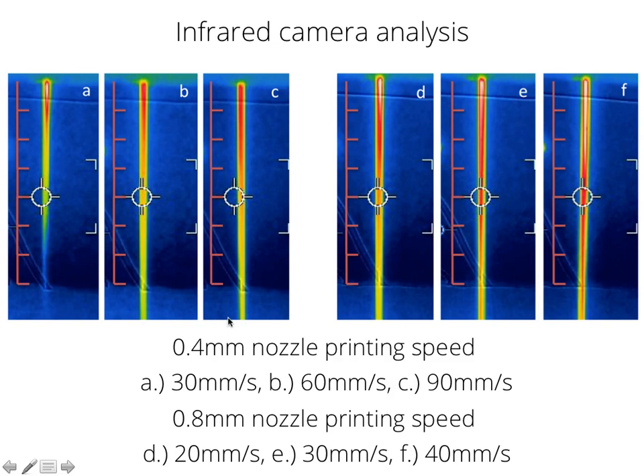However, as you can see here, it seems that both of them reach the same temperature after the same amount of time, the same amount of length, and you create here a much bigger surface area per time than you do for the 60 millimeters per second. So this means the 90 millimeters per second must cool down faster than the 60 millimeters per second. But still, you would say just from the images, these two would emit the same amount of particles because the same length of filament stays hot for the same amount of time. So the surface area temperature hypothesis only fits, well, okayishly.